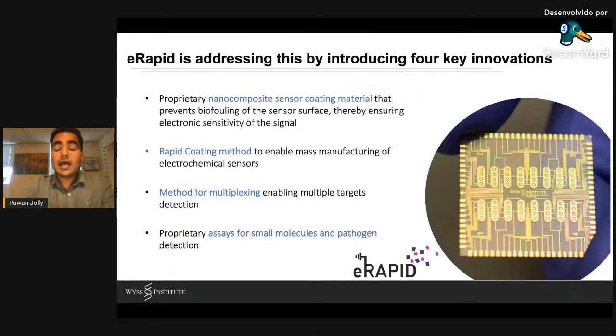So the eRapid technology is addressing some of these key challenges by introducing four key innovations. So first one is our proprietary nanocomposite coating, which can be simply drop casted on electrochemical sensors, which maintains the electronic sensitivity. The other one is the method by which we are coating. So we have developed a rapid method that enables mass manufacturing of electrochemical sensors. We have our own strategy of multiplexing, which when coupled with this surface chemistry enables very specific and sensitive detection of multiple targets on the same chip in the single channel without having any complicated microfluidics.